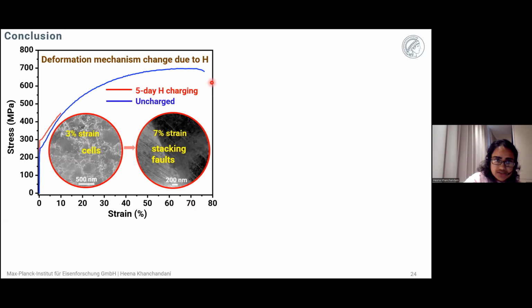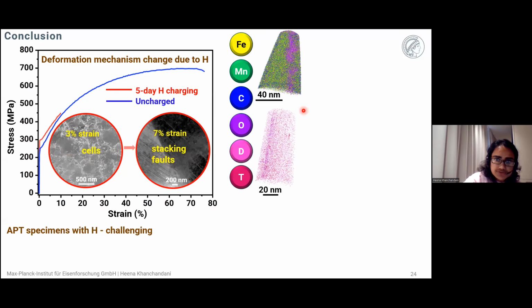So in order to conclude, we observed that there is a change in the deformation mechanism due to hydrogen from the formation of dislocation cells to the stacking faults. But in order to really understand the mechanism, we had to find the ways of charging site-specific atom probe specimens with hydrogen, which was really hard and challenging in this case. But when we found the ways, we observed that hydrogen segregation at these grain boundaries leads to the early embrittlement of these materials. And it also shows that not only hydrogen, oxygen is also responsible for the embrittlement of TWIP